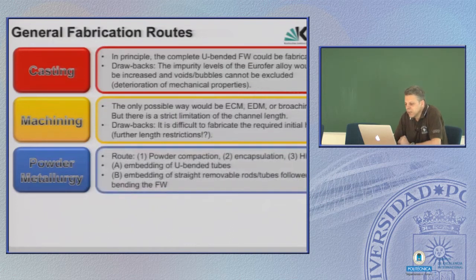Powder metallurgy is a standard fabrication route in many cases, and it would also be possible with Eurofer. You could produce powder from Eurofer, that's not a problem, also not too expensive. In general, the powder is compacted, then encapsulated in standard steel or whatever, put into a hot isostatic press, and then it's finally compacted near to 100%. This is possible. So 2 ways could in principle be thinkable by powder metallurgy.